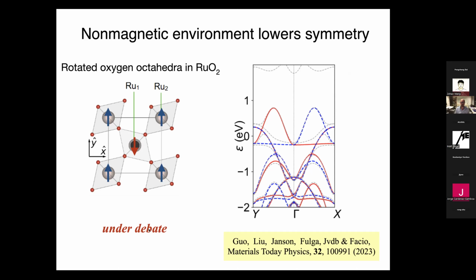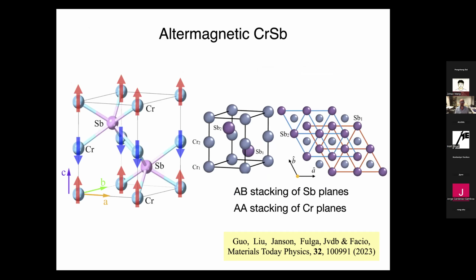As I said, this is not the best example of an altermagnet, but if you look at the band structure, for ruthenium dioxide with a finite magnetic moment, you'll see that if you go along gamma X, there is a certain ordering of the bands, and the blue and the red are the spin up and the spin down bands. If you go to gamma Y, which is a direction at 90 degrees from gamma X, there are the same bands, but with opposite spin.